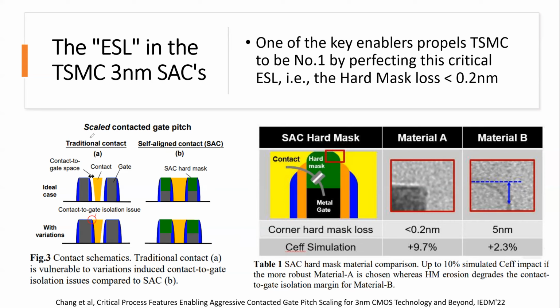Before going that deep, let's look at the traditional contact. All right, you want a contact here, so it's a drain here, and then the traditional one is put very close. All right, and that's what you hope for. But there's a gate-to-contact isolation, as we mentioned here. If you have something going on here that you're not protected, then your etch or your deposit is going to interact with the gate metal here, then you're doomed. You cannot have any reaction here at the tip of the contact and gate.